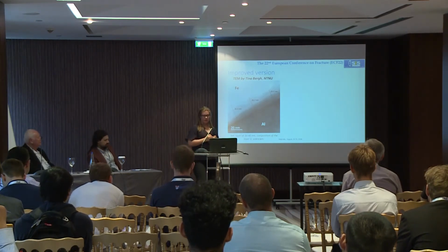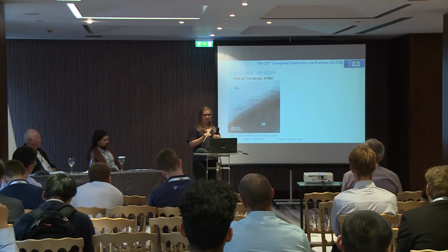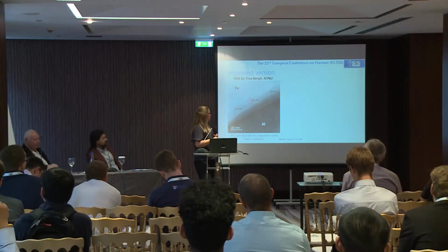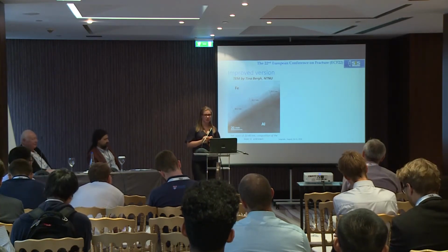This is also quite interesting, since if you have a small layer, you need that to have a bonding. If the intermetallic layer is too thick, the brittleness of these phases will cause a brittle bond. And yeah, she's now working on figuring out which chemical composition these layers have.